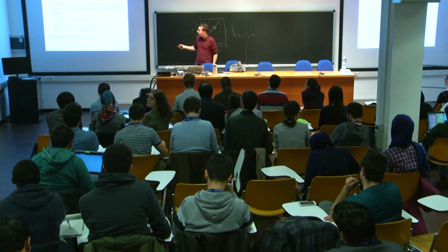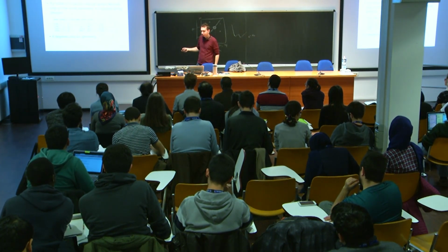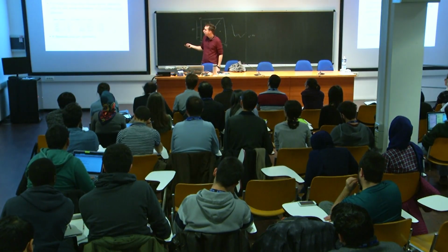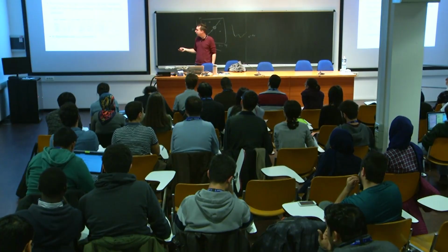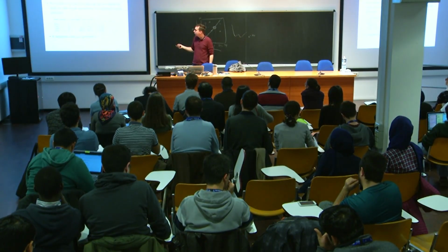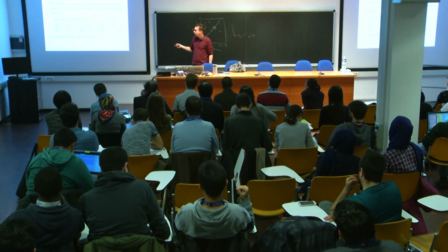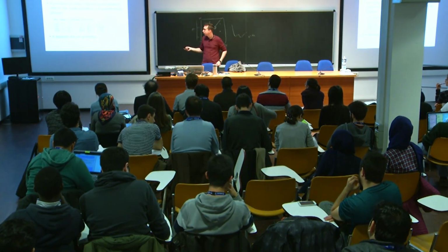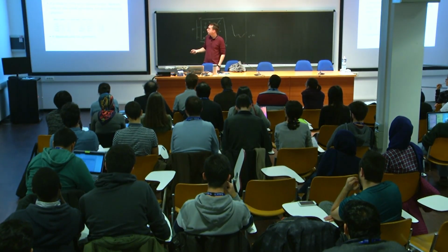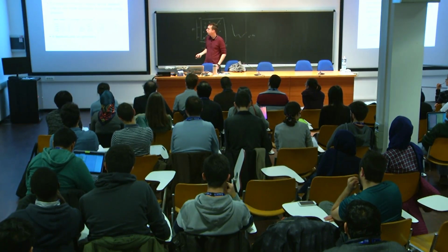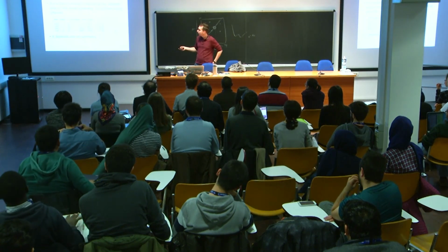But what interests us in this case is the last column, which can have a capital I or capital R, and this just means whether the mode is infrared active or Raman active. It is possible that a mode still has zero Raman or infrared cross-section even with the letter here, but the opposite is not true. If there is no I or no R here, there is no chance the mode will be measured with a simple infrared or first-order Raman spectroscopy. So it only depends on symmetry.